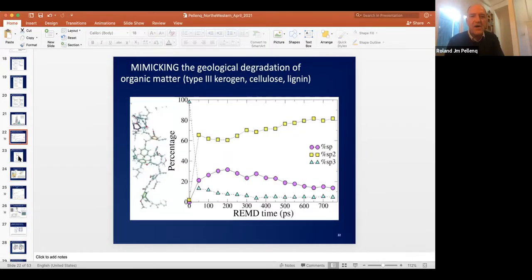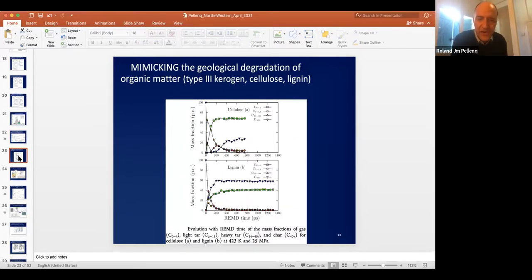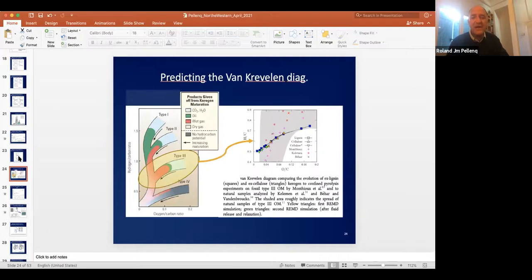All right, so now we can analyze further the cellulose versus the lignin. And clearly the lignin is producing the largest chunks of carbon. You see the C40 plus, the number of carbons, is actually bigger in lignin than cellulose. So cellulose is producing smaller units of carbon, while lignin is producing more of a percolative structure of carbon.